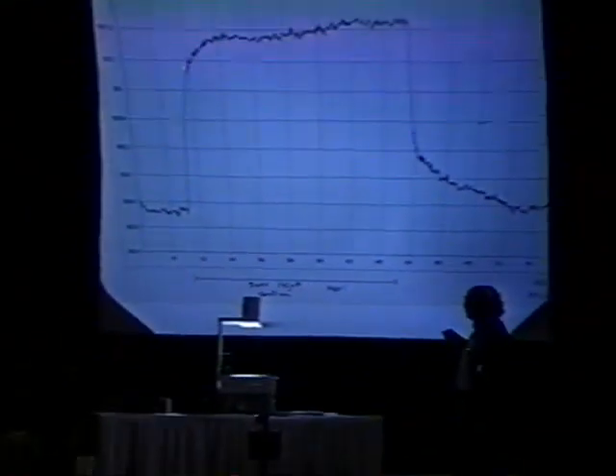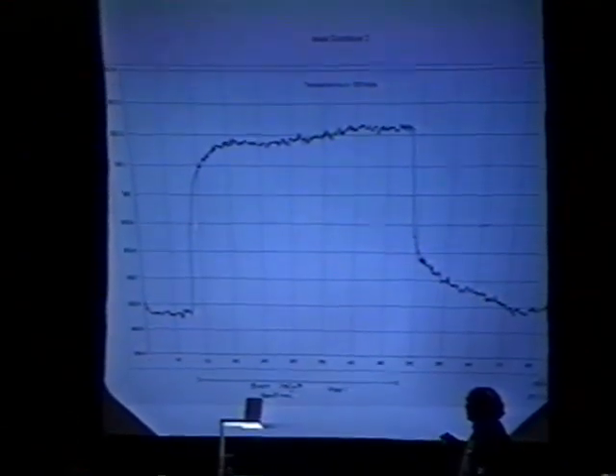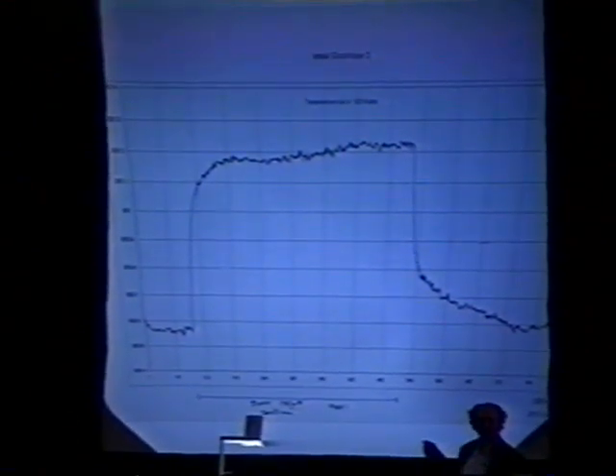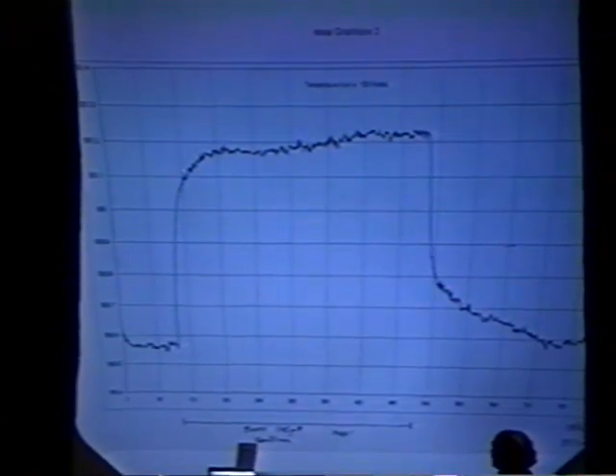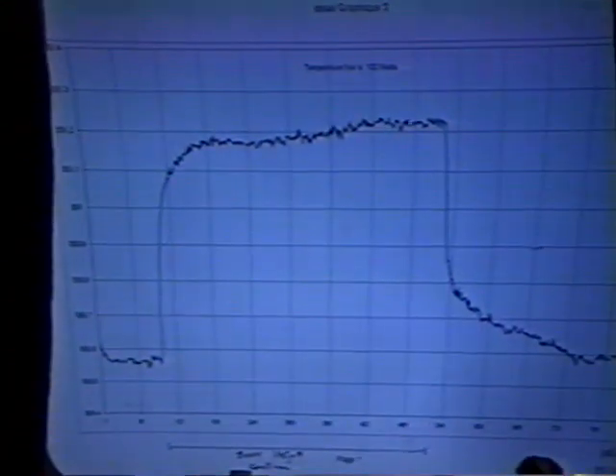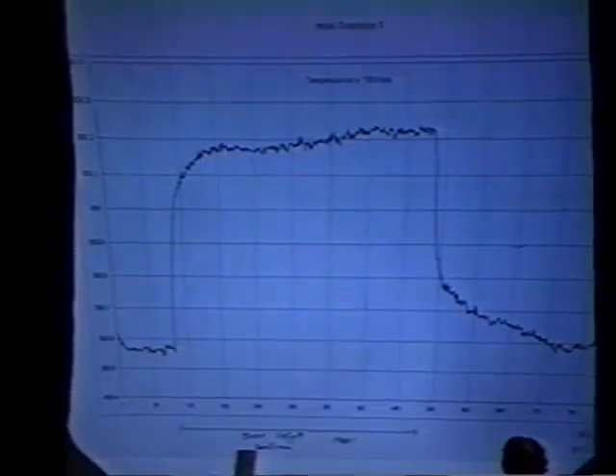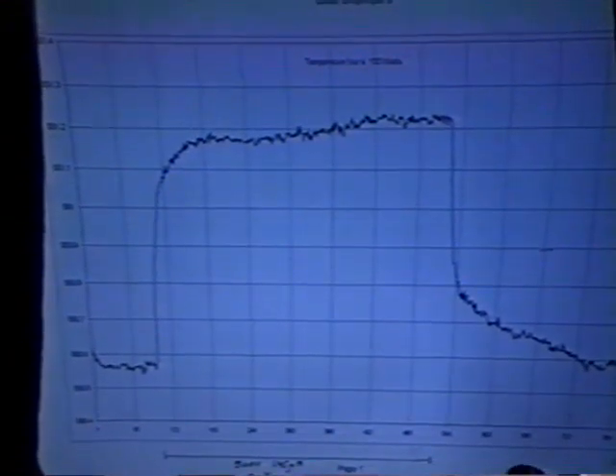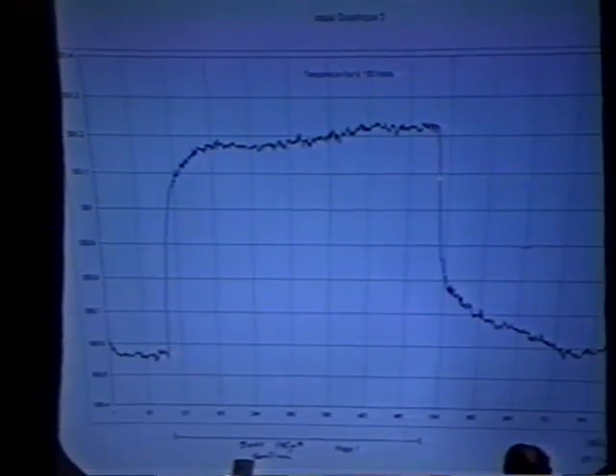Now, what we notice is that this is very fast. It takes about 10 minutes. The time constant of the system is about 10 minutes. And then there's a slow increase. Now, after, I don't know how many hours, 1, 2, 3, 4, 5, 6, 7 hours, we turn it off, and then the temperature decreases. That's fast, same time constant. And then a slow decrease, about 2 hours.